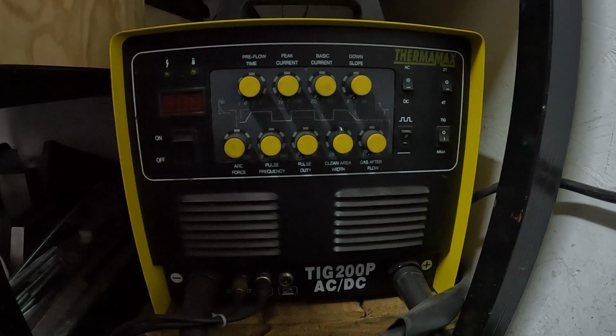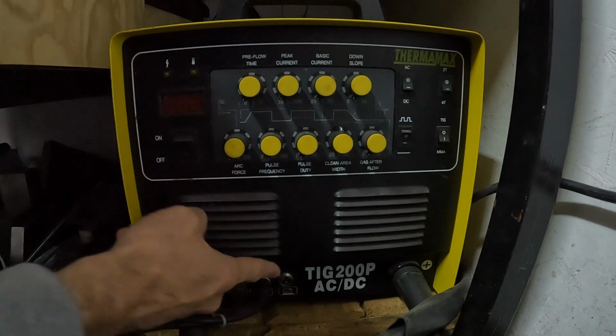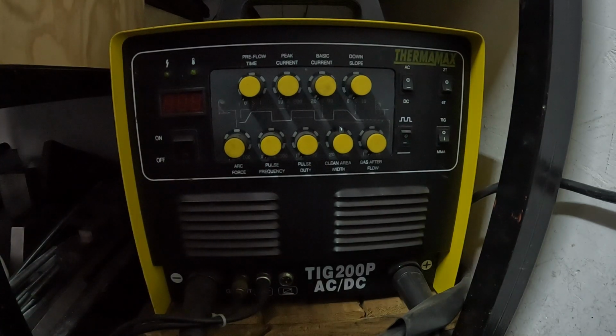Another thing you need to do with AC welding, and specifically with aluminium, is you do need a foot pedal. Reason being is your first strike is typically a much hotter strike, and then you can push back as the material heats up. An interesting point on the pedal, if you're doing highly specialized welding with, say for argument's sake, boilers with the stainless steel, there's a welding qualification that you need to do, and that's that WPS that I showed you right at the beginning of the video. If you weld with a foot pedal, you don't actually know what current you're welding at. It could be your maximum setting or somewhere between your base and your maximum setting. So you would very seldom walk into a welding shop where they're doing qualified welding procedures with a foot pedal. Typically, they stay away from the foot pedal just because you never know where you are with your welding. And engineers don't like welding if you don't have the very specific amps that they specified, and rightly so.